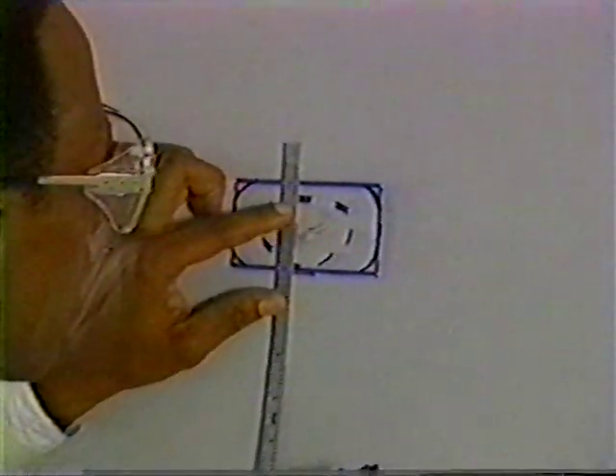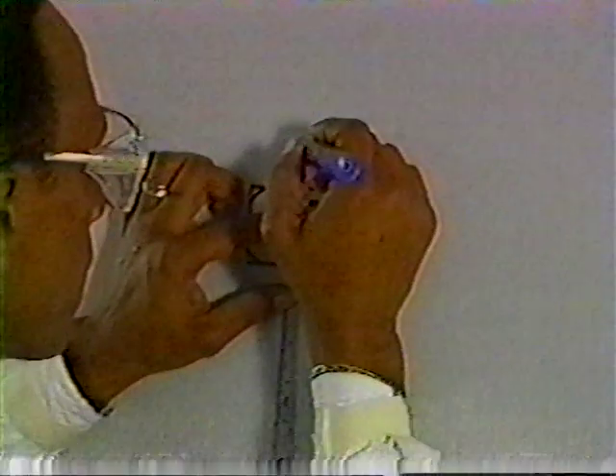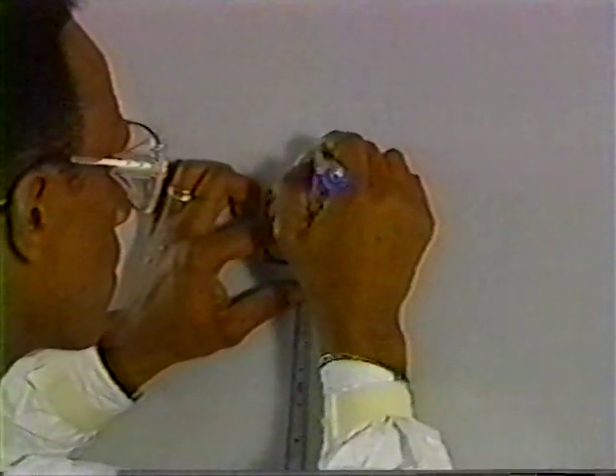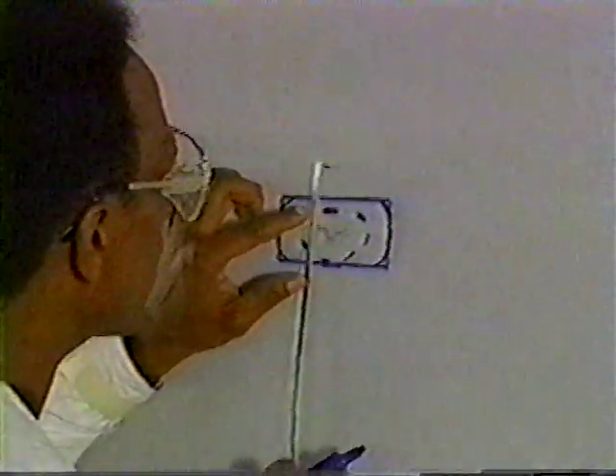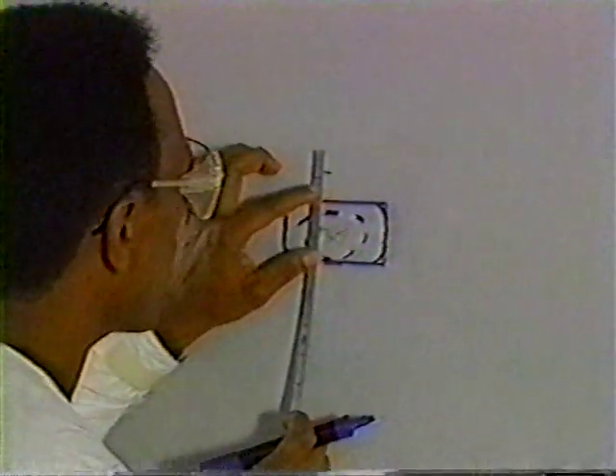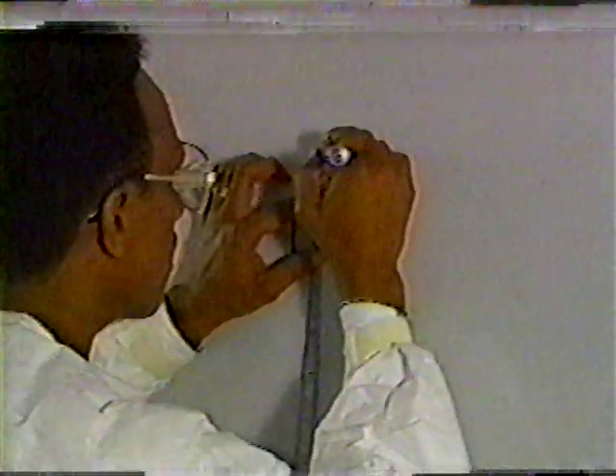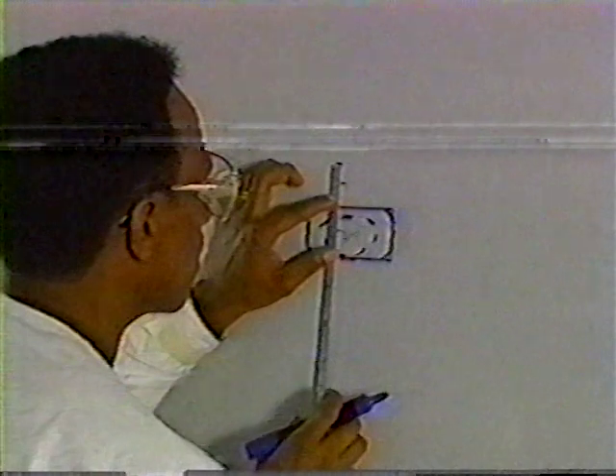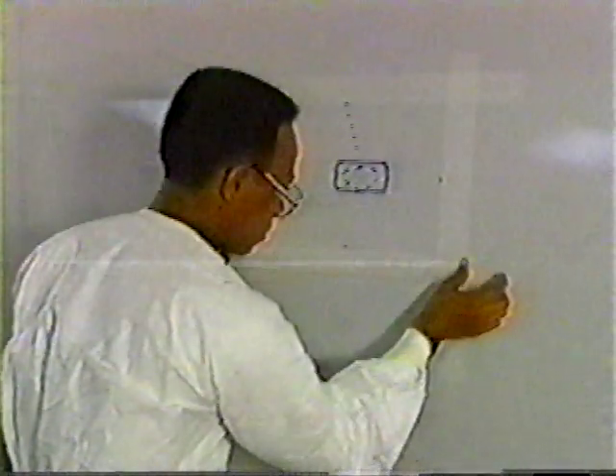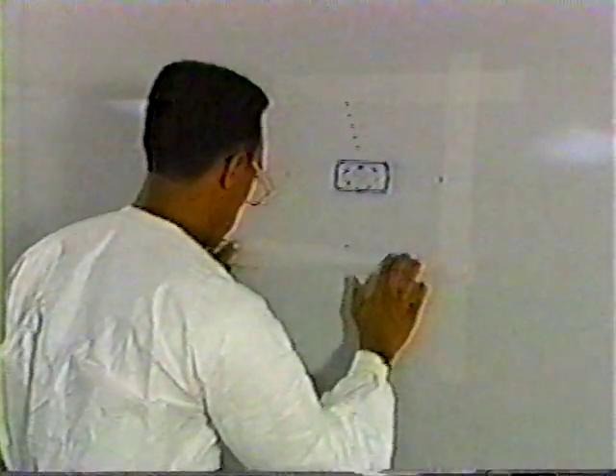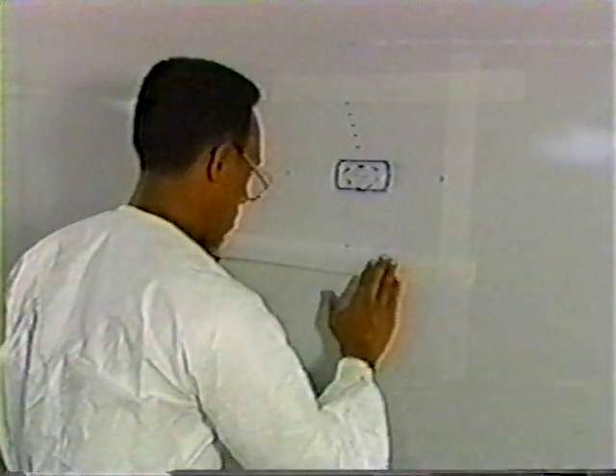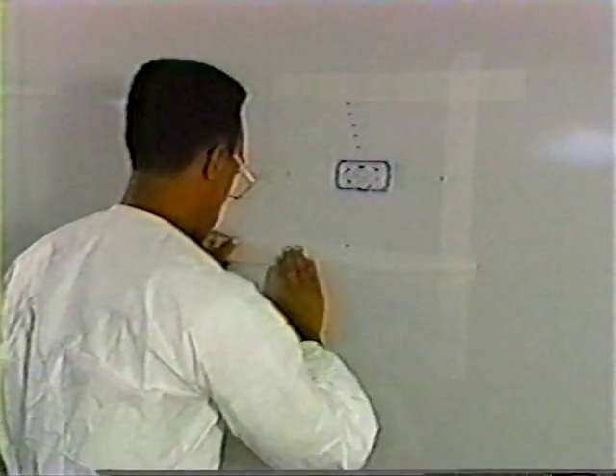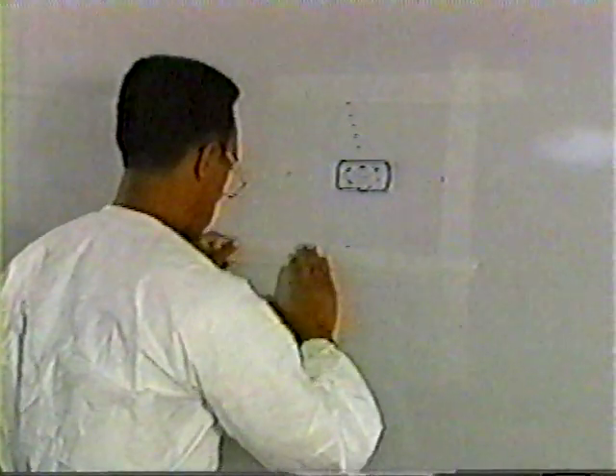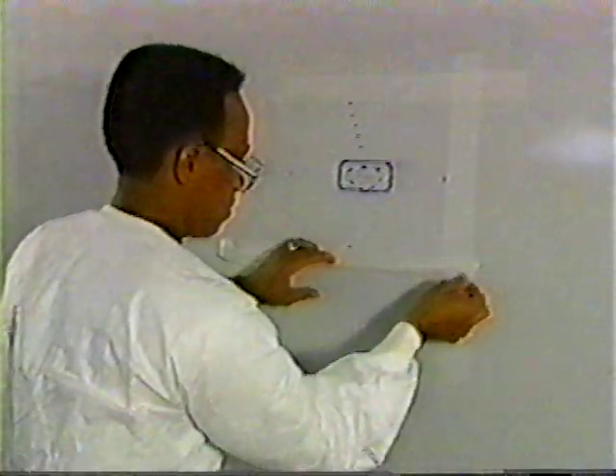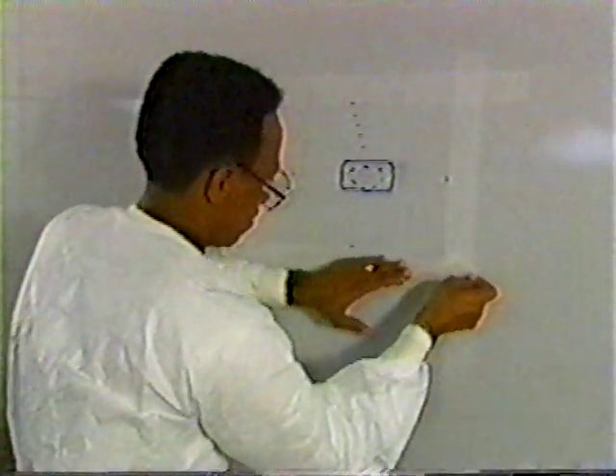Next, measure the distance from the edge of the cutout area, marking the location of each repair ply as well as the location of the sanding ply in order to determine where the Teflon tape barrier will be located. Then, place a strip of 2-inch wide Teflon tape around the repair area, making certain it is positioned just beyond the border where the sanding ply will later be placed.